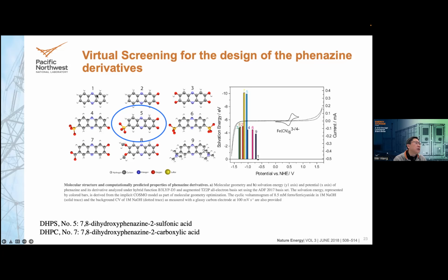So this is a phenazine structure, the number one, a pristine structure. This one, we know it has a good electrochemical property, but it barely dissolves in the water. So we have to make it somehow have a good solubility. There's quite a bit of different functionalizations that have been proposed, and we did a DFT calculation to figure out what those functionalizations will do to its redox potential and also the solvation energy. By this way, we can identify two of the good ones. One is with the sulfonic acid functionalization, and this is the one we choose to achieve both ideal redox potential and high solubility.